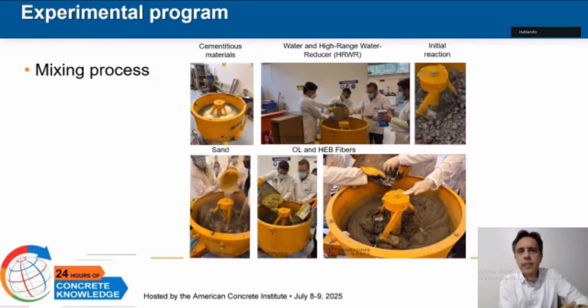This slide illustrates the controlled mixing sequence for both SCC and UHPC mixtures. First, we introduce all cementitious materials, including cement, silica fume, and mineral additives. These materials were dry mixed to ensure homogeneity. Next, we gradually added the mixing water and the high-range water-reducing admixture. This stage starts hydration and enhances the dispersion of fine particles.